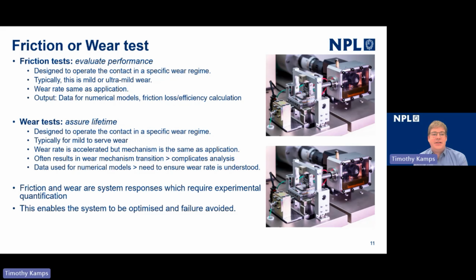Frequently with friction tests, the objective is to produce mild or ultra-mild wear, and in doing this, produce data for numerical models that allow friction loss and efficiency calculations. When we look at wear tests, where we're looking to assure lifetime, what we're doing in this case is moving a contact to the maximum power that can be dissipated while the wear mechanism is representative of the normal operating condition, i.e. the maximum wear rate without transitioning to a different wear mechanism.